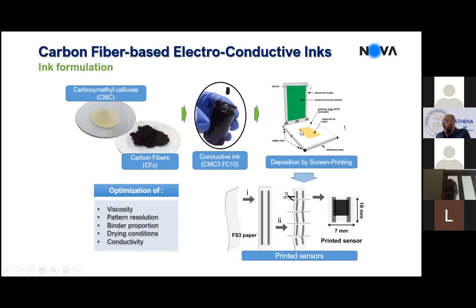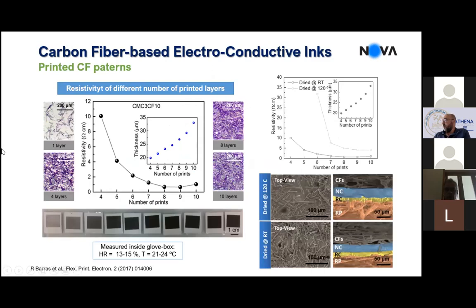And we were using screen printing for this technique. And you can print conductive layers, you can print the sensing layer. So you have the ink that contains carbon fibers and cellulose, okay? And we analyze what are the properties of these printed patterns. If you look, we have fibers dispersed in the cellulose binder. So the CMC, it's what keeps the fibers together. You need to adjust the quantity of the carbon fibers that you have in the layers that you are printing, in order to have a percolation path for current, because these will be resistive sensors.